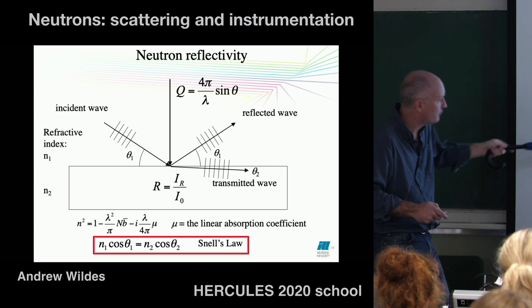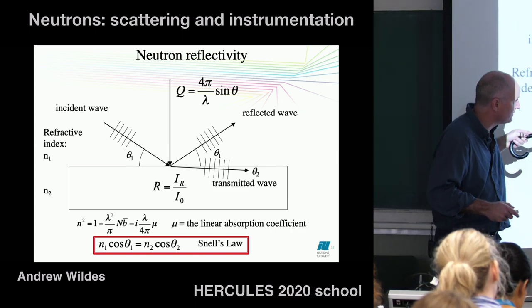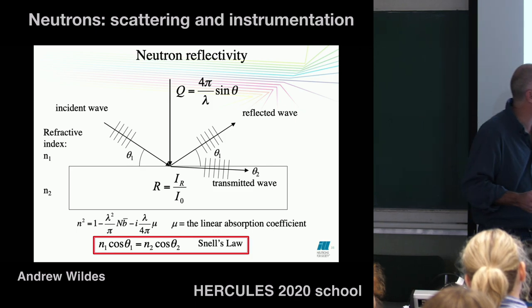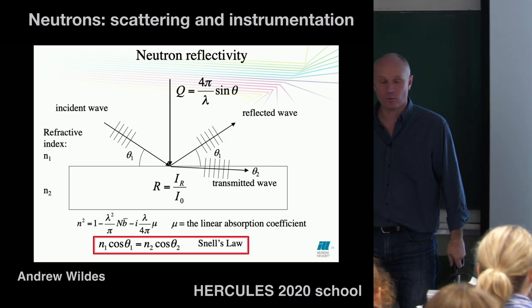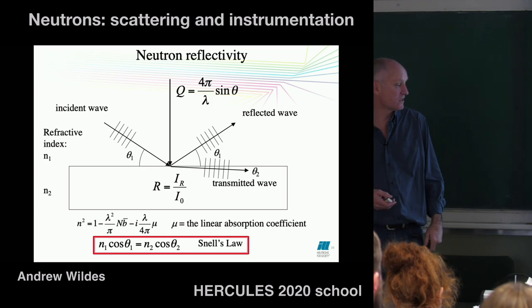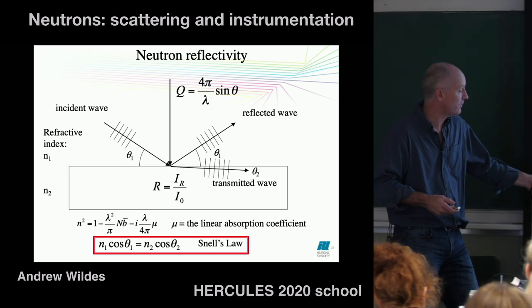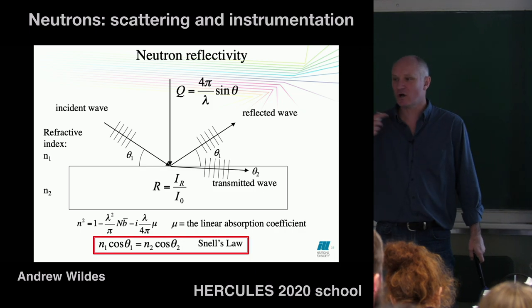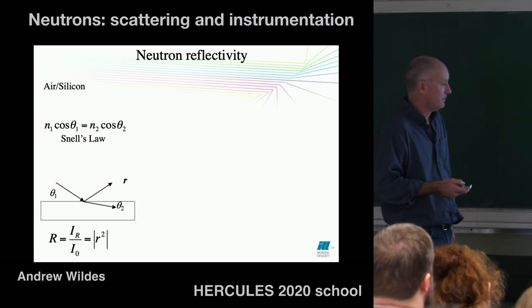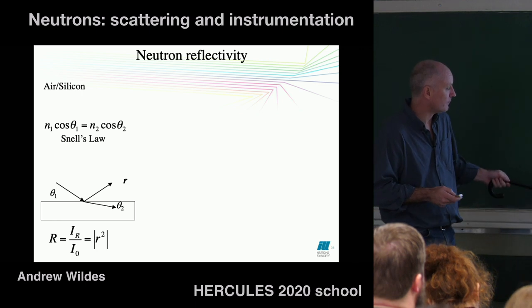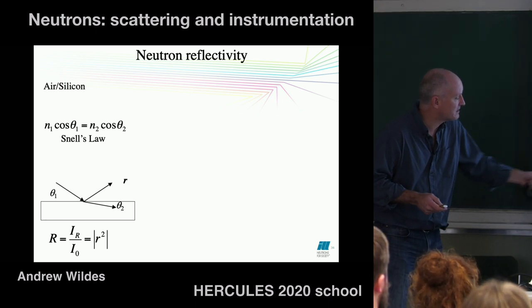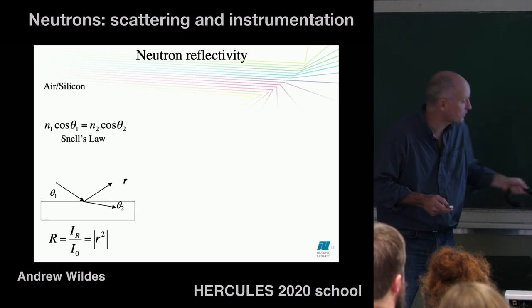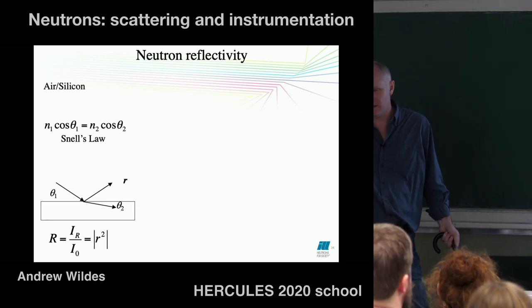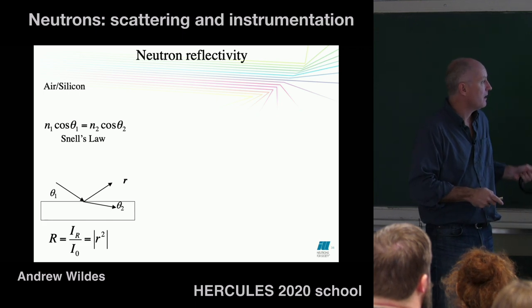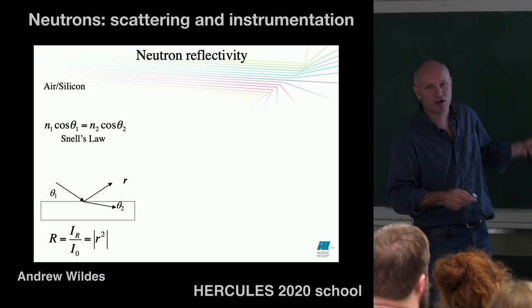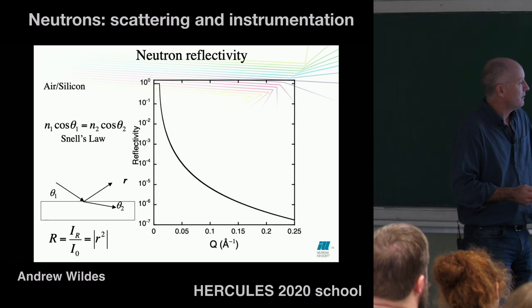If you look at these angles, the angle of incidence and angle of reflection are of course the same, but then you've got an angle inside the material. This is the refracted wave, and they're related through a law called Snell's law. So you've got these two angles and the two refractive indices. If you try and plot that for neutrons, this is also true for X-rays, by the way, you can get the reflectivity, which is given by this quantity here. It's the reflected intensity divided by the incident intensity. If you plot that for neutrons, and here's an example going from air to silicon, you'll get something like this.